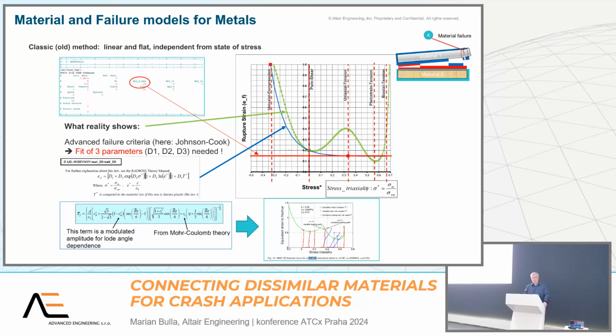You can use for this, for example, some analytic models which exist, like the Johnson-Cook failure criteria, which gives you this kind of shaped curve, which is better than the flat line. It distinguishes between failure in compression versus failure in tension, which is good. Or even a more complex one, the modified Mohr-Coulomb, but try to fit these beasts. So this is such an equation. It's a challenge.